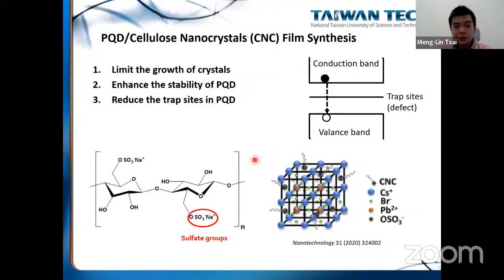And recently we tried to combine it with cellulose crystals, which are derived from biological plants. We use functionalized cellulose crystals, and we expect that the functional groups can have some interaction to stabilize the crystals. Of course, it can also act as an encapsulation polymer or organic material to further protect the perovskite quantum dots from various environments.